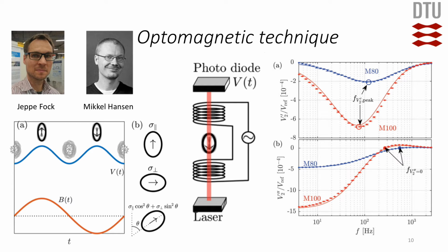The technique is based on anisotropy of magnetic nanoparticles that have an ellipsoidal shape, and they are able to follow an oscillating magnetic field. Depending on their hydrodynamic size, they will align along the magnetic field to a different extent, so to say.